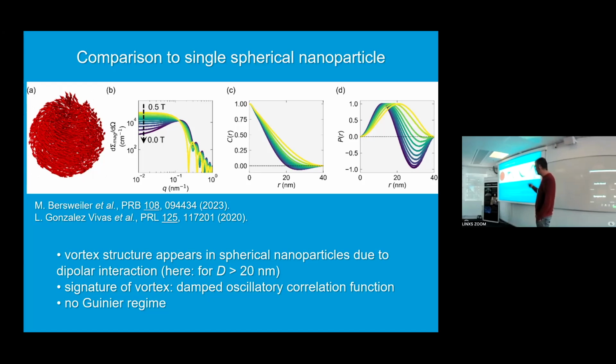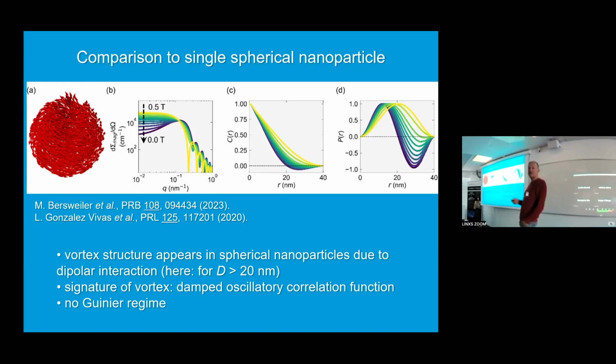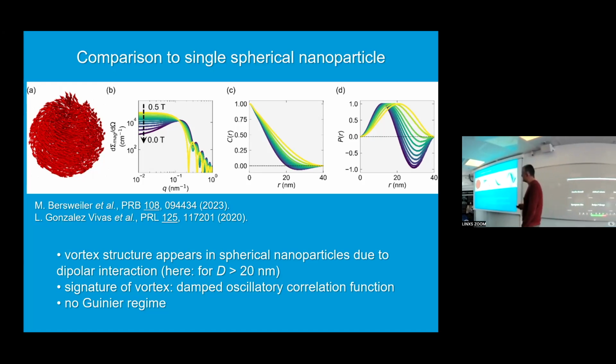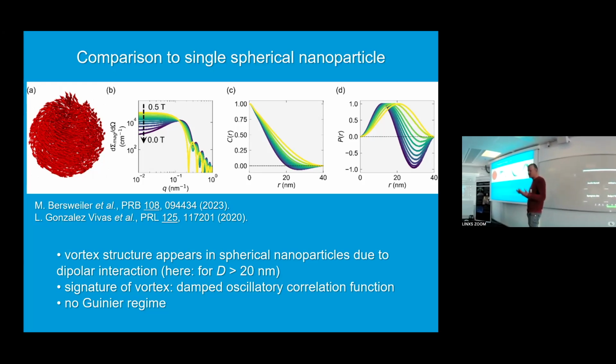And that, of course, we can use to provide an explanation for the experimental result that we have seen in the neodymium magnet. In this simulation, we have all the energy terms that I mentioned before. If we leave out the dipolar interaction in these simulations, then we simply get a single domain. We get Stoner-Wohlfarth behavior.